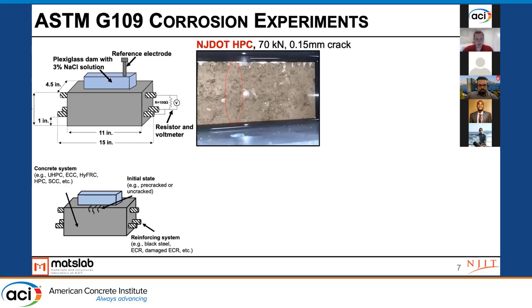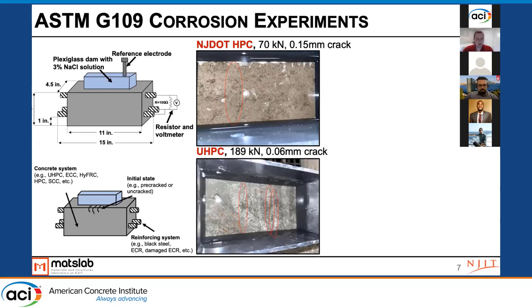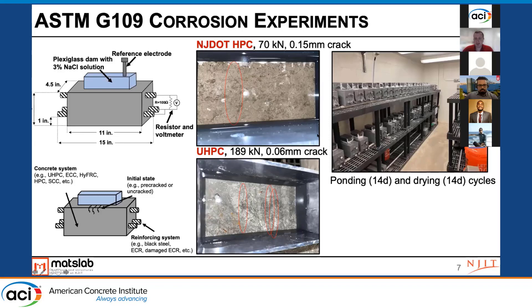Looking at the surface of one of these beams, this is one specimen with just a standard high-performance concrete mix, loaded to a representative service load. We observed the cracking that occurred. We did similar type of loading for all the materials — looking at uncracked and cracked conditions. The UHPC gets to higher load levels before you see cracking, and so it would have a higher service load level as well, and you can restrain crack widths. All these specimens are sitting in a 50% relative humidity room and go through 14 days of ponding and drying to accelerate the time it takes for chlorides to move through the system.